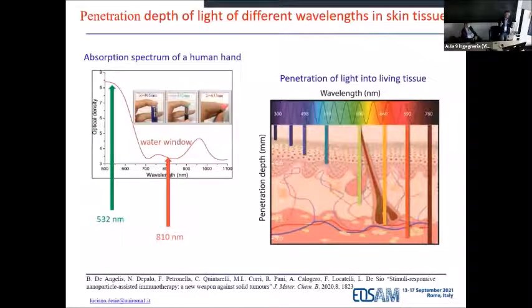And there is another issue. We are working with a green light where the absorption of the tissue is very high. There is no penetration with green. Much better if we can work with a near-infrared laser, the so-called water window, where the transparency in the tissue is very high. You can see here these simple photos. Blue light cannot go through. The same for green light, but reddish light can very easily propagate to the screen. You can do this with your smartphone. You have a torch, you just shine it on your finger and you will see the reddish light. It means that this longer wavelength can penetrate through.